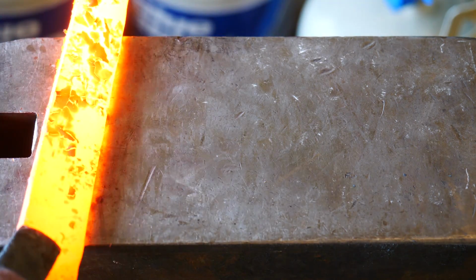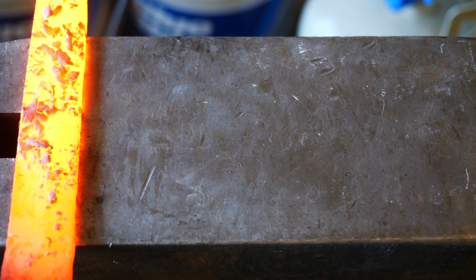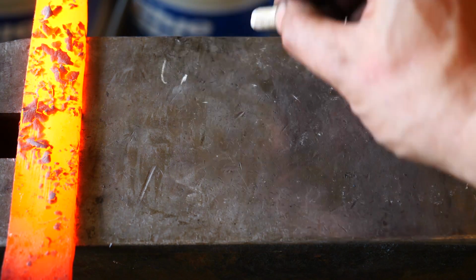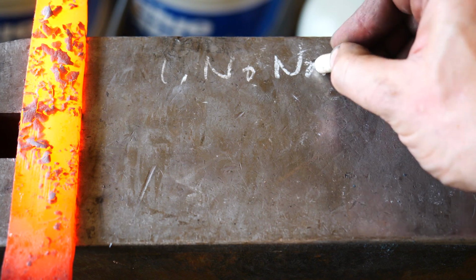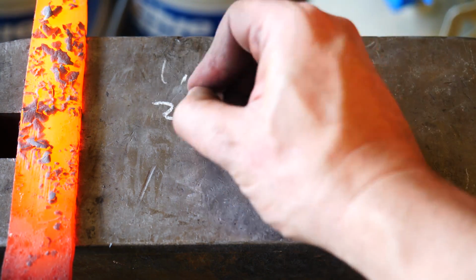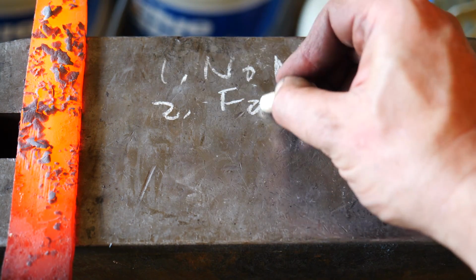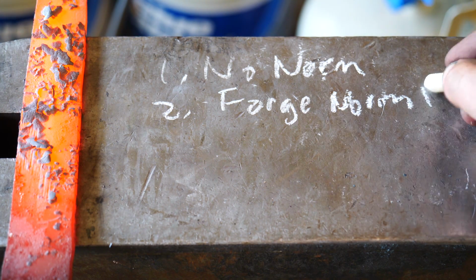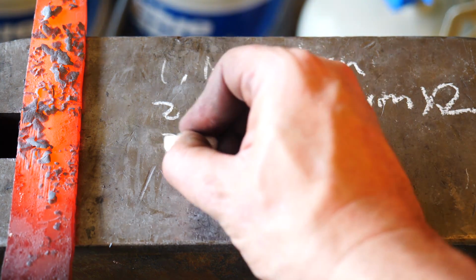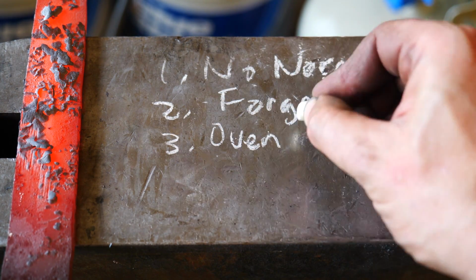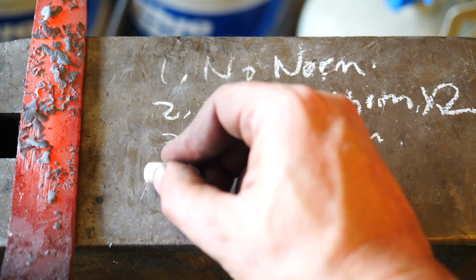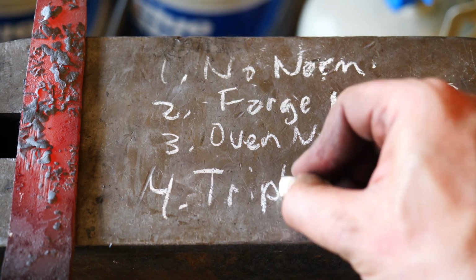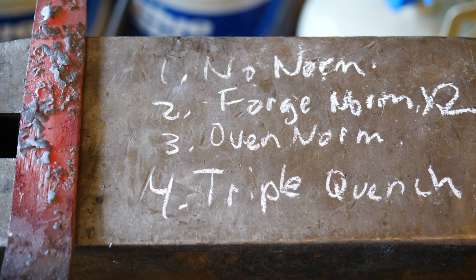We're going to try 4 different quenches. Number 1, no normalization whatsoever, but we'll quench from a temperature-controlled oven. This may suggest whether normalization is useful for grain size at all in 5160. I think it should be. Number 2, forge side normalization times 2. Then apply a single quench from the forge. Number 3, oven normalization and quench from the oven, temperature-controlled. Number 4, forge side normalization times 2 again, and the triple quench.